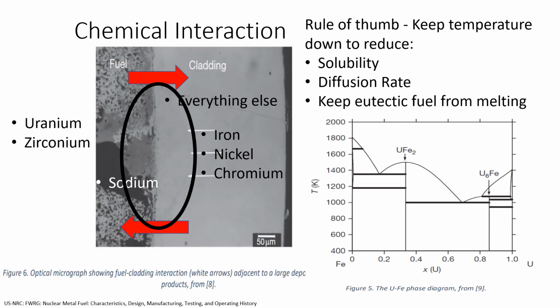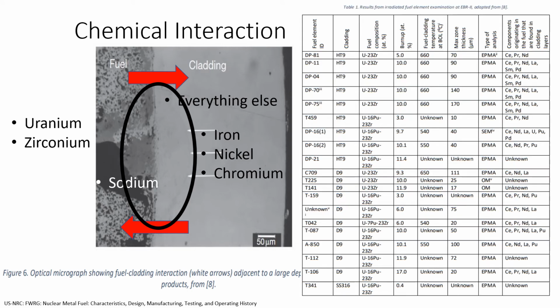Experiments were done with 2 different fuels and 3 different claddings, and cross-sections were taken and studied. Results are reported in Table 1 using different conditions. Pellet-clad interactions ranged from 540 to 600 degrees Celsius, and some zones were up to 170 microns thick, or 0.17 millimeters thick, of diffused material. Burnup also plays a significant role due to the porosity and sheer number of elements present. Highly interactive areas are also believed to be the areas where the cladding will first fail.